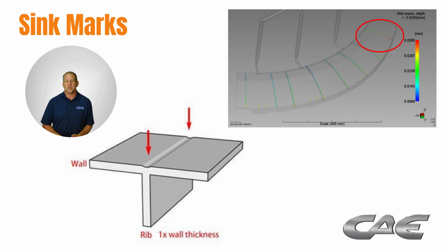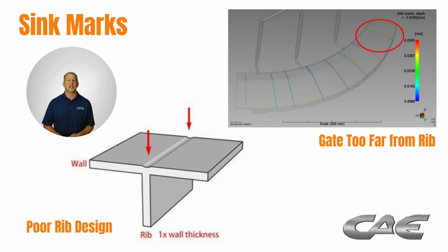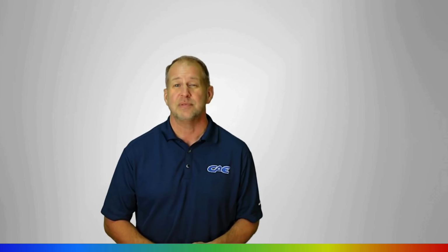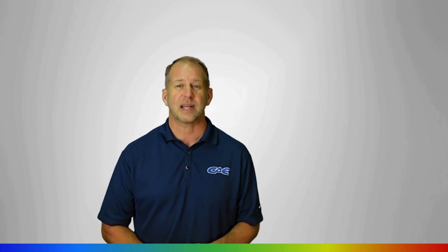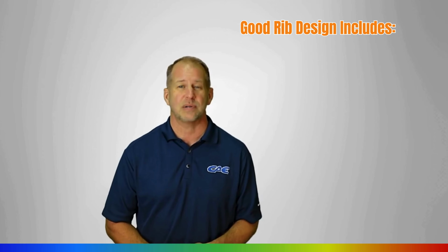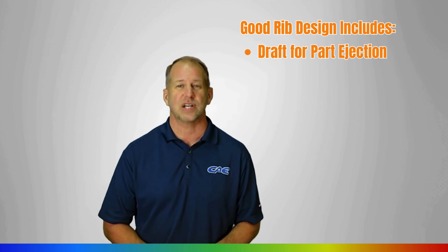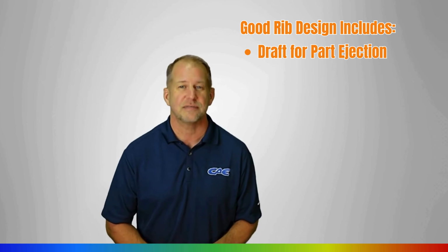Other design flaws to watch out for include sink marks caused by poor rib design or inability to pack those areas because of poor gate placement. Poor rib design can appear where draft angles are misapplied. Adding a slight taper to walls is necessary for easier part ejection from the mold without damaging its surface.